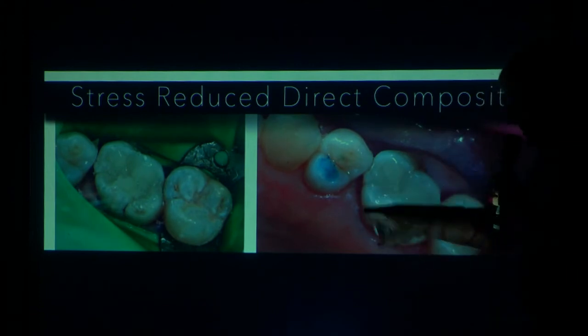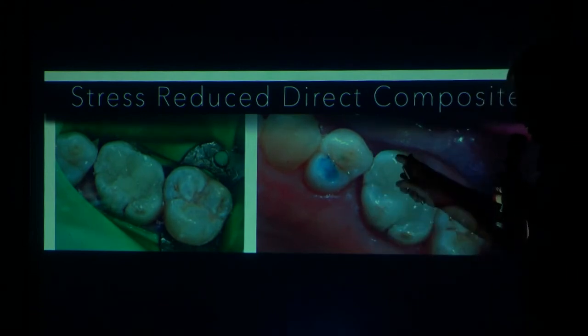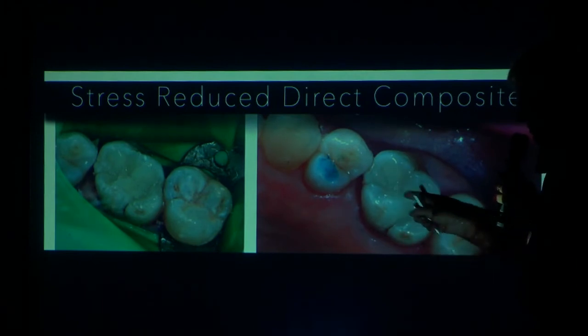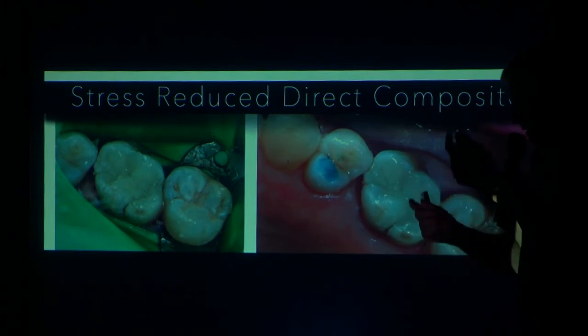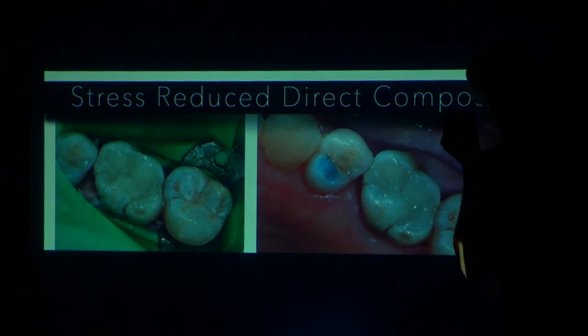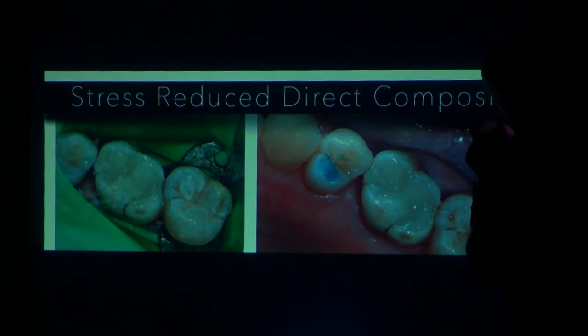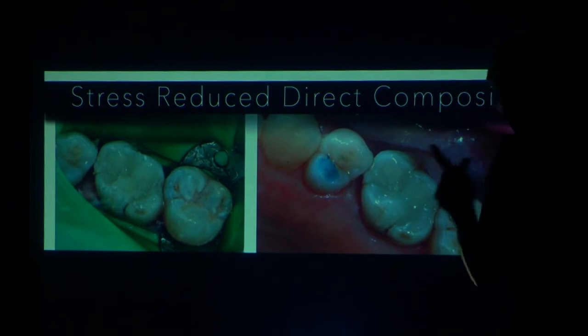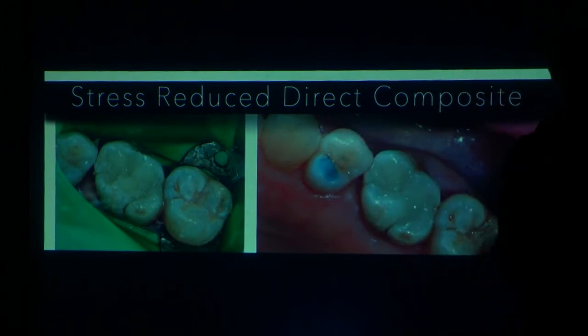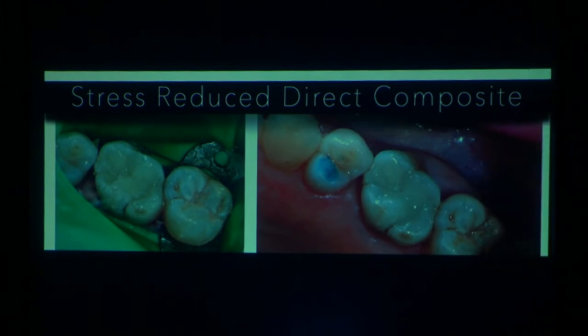But these cracks, remember, once you connect the tooth side to side, front to back, and top to bottom, like Davey taught you, the expansion of the tooth goes to about 7 microns. If it's not connected side to side, then the expansion that caused these enamel cracks is about 175 microns.